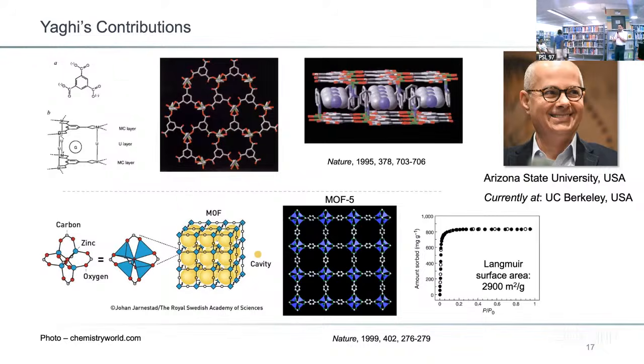But more importantly, when he measured the surface area, he found that this particular material has 2,900 square meters in 1 gram of the material. So the original example that I showed of the football stadium and things like that, these guys already started getting there, because in this example they got halfway there, which is about 2,900 square meters per gram. And despite having that much porosity, this structure was completely stable. So the moment you took out the gas molecules, which are these yellow balls, the structure was not collapsing. So now we have a house that is stable enough to insert gas molecules and to remove gas molecules as well. So this was one successful experiment that Yaghi's group did.